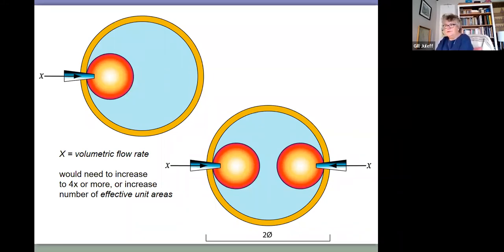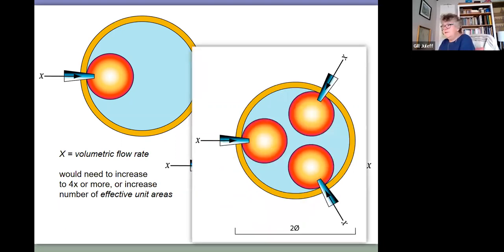you make your furnace larger, but you immediately hit a problem because you have to blow in more air, and most effective unit areas are optimized for the amount of air you're able to blow into it. So if you want to double the diameter of your furnace, you've got to blow in at least 4 times more air, or you've got to increase the flow rate by 4 times. A better way to approach that would be to increase the number of effective unit areas. So now you've doubled the diameter of your furnace, you've added another unit area. More effective would be to put 3 in there.